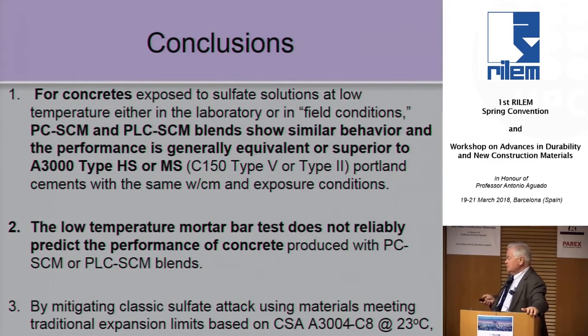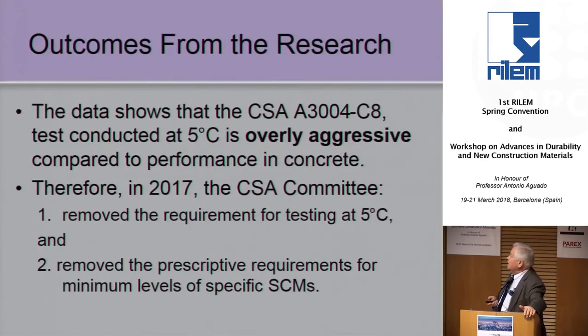And then we found that the traditional mortar bar test we did, the ASTM C1012 test, at room temperature was sufficient for telling us whether a system is mitigated or not. Because if you mitigate it for ettringite, you also mitigate it for Thaumasite, is our finding of that. So the test was too aggressive, so last year we removed the test method from our standards that had been there since 2010, and we've now removed all the restrictions on the use of limestone cements in sulfate exposures.